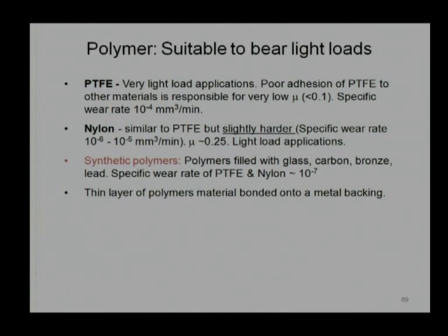PTFE is mixed with some other polymers to retain the low coefficient of friction and the low wear rate. So, both low wear rate and low coefficient of friction are achieved by hybridizing with other polymers or other components. That is why we are saying that if PTFE is mixed with glass or carbon fibers, they increase the strength. When they increase the strength, the wear rate goes down, and it has been observed the wear rate turns out to be only 10 to the minus 7, compared to 10 to the minus 4, almost a 1000 times increase in life when we are using synthetic polymers.